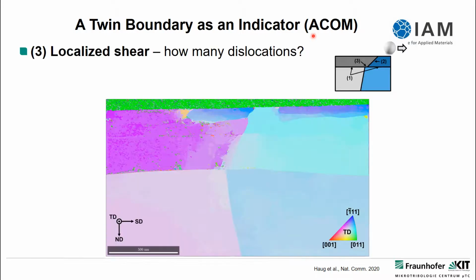This is what you can see here, the ACOM result, color-coded in transverse direction. You can see here the inverse pole figure, so a red color corresponds, for example, to a 100 orientation. What we see above here, this green color code, is the platinum that is deposited prior to cutting the TEM foil.